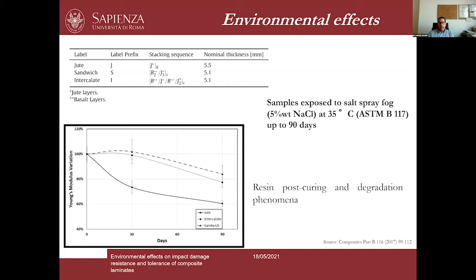And of course, they do not absorb a large amount of water compared to jute fibers. And these composite materials were realized in two different hybrid configurations, a sandwich configuration and an intercalate configuration. The difference is simply how we stacked the different layers together. And this composite material was subjected to a salt spray fog test up to 90 days. And then we analyzed the results on these composite materials from a quasi-static point of view, for example, performing flexural and tensile tests, and also analyzing what happens when we subjected these composite materials to a low velocity impact.